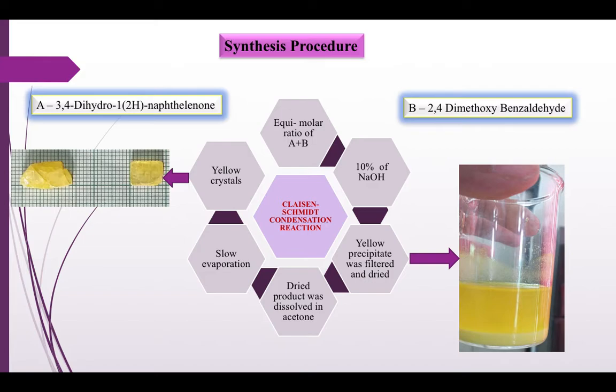To which 100 ml of absolute alcohol was added and stirred until a clear solution was obtained. A freshly prepared 10% NaOH solution was added to the resultant solution and stirred for 2 hours. This solution was kept at rest for 24 hours at ambient temperature. A shiny yellow precipitate obtained after filtration was washed several times with water to remove any traces of NaOH. The filtered and dried product was recrystallized twice in acetone to purify. After a week, yellow block crystals were harvested with an 85% yield.